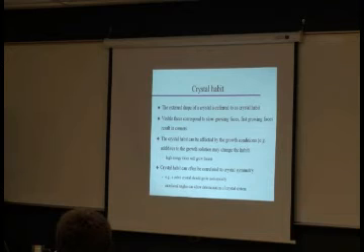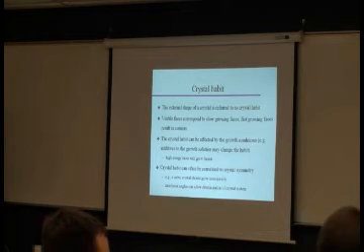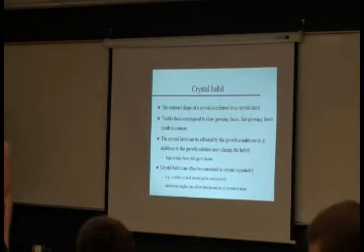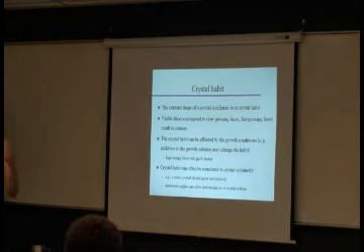This one is actually the same material. Okay, but if you look at these more closely, you will see that the big shape-defining things that you can probably see right now from where you're seated are similar to the ones over there, but then it looks like each of them is growing a little hedgehog on them. Okay? Very interesting crystal shape. How did that happen? Well, we started growing some crystals and then the conditions changed. So all of a sudden, nucleation became very fast. So you had a lot of new seeds depositing on the surfaces of these crystals, and each seed started growing. That is how you get this kind of hedgehog on the crystal shape.